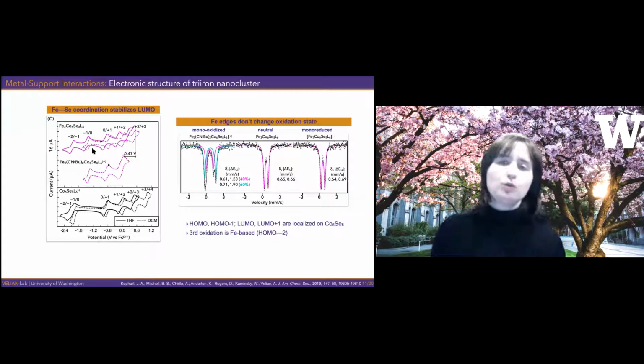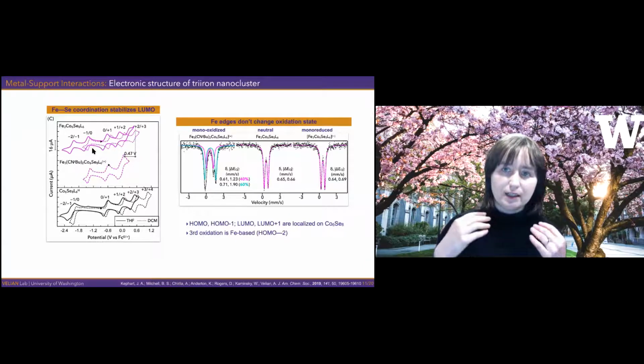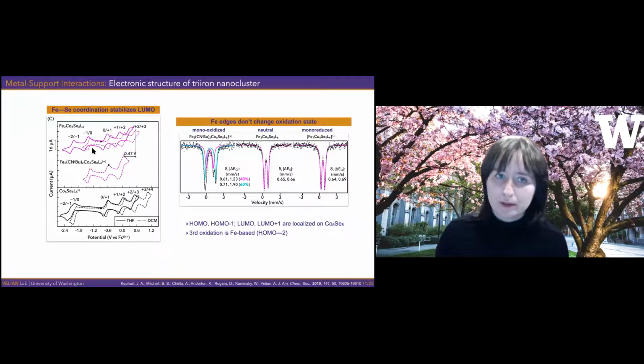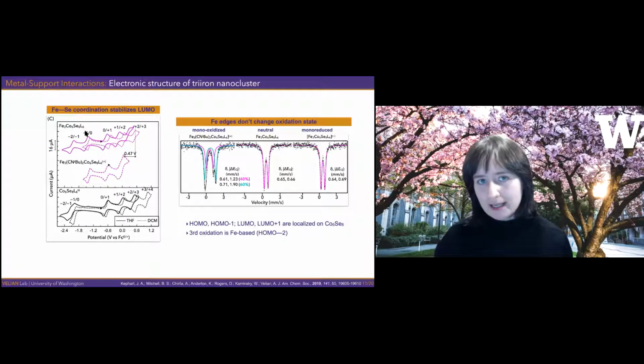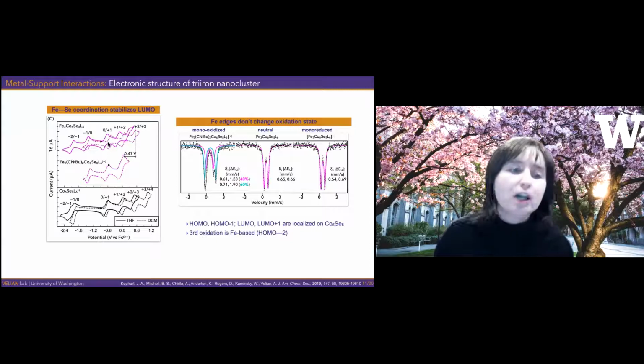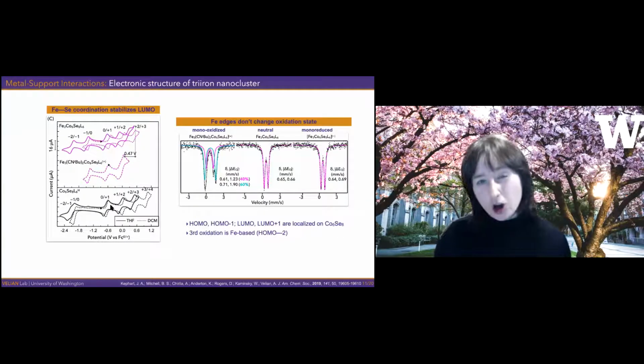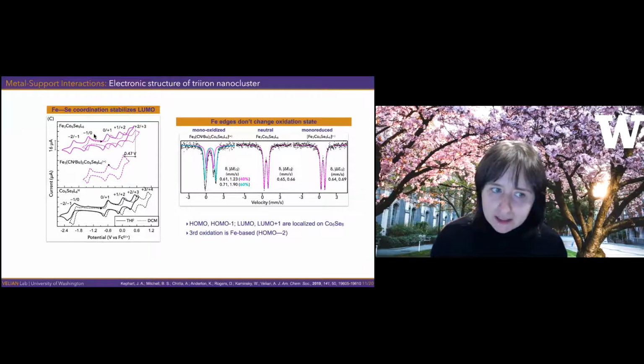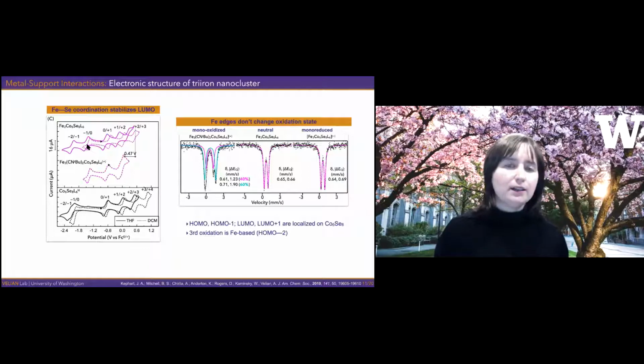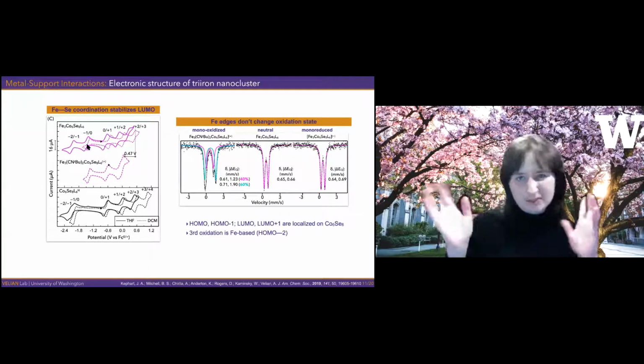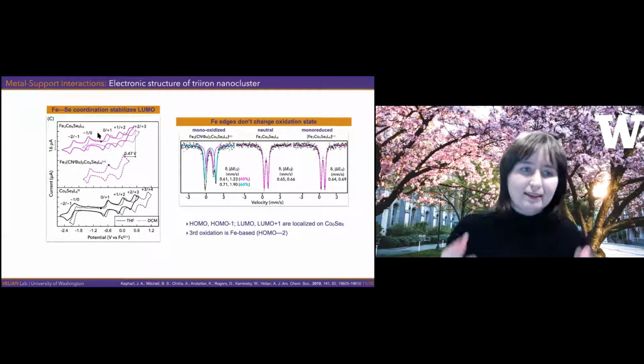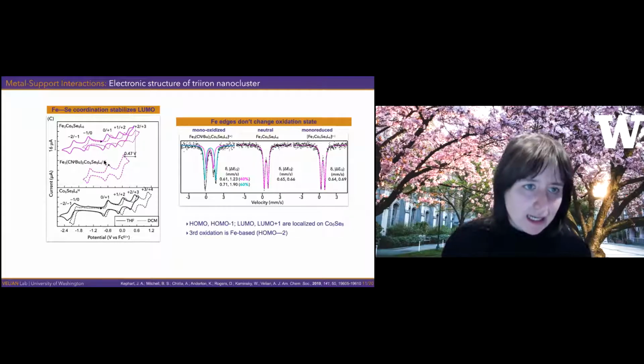So the first reduction, which we use as a proxy for the lowest unoccupied molecular orbital, so the LUMO level, is really stabilized by the iron selenium coordination. Okay, even if we are pretty confident that the LUMO as well as the HOMO, the highest occupied molecular orbital, are both localized on the cobalt selenide core, the LUMO is really stabilized by this. It's as if the iron is removing electron density from the selenium, kind of like a Lewis acid might, and then it's easier to put an electron on the core as a result of that. That's sort of a hand-wavy, intuitive way to think about it.